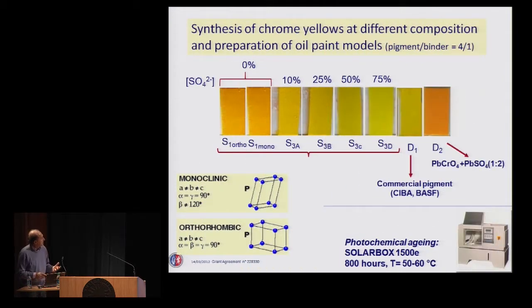And so what Letizia did to better characterize the knowledge concerning this pigment was to synthesize different composition lead chromates, and also those having different crystalline structure. So these are mock samples layered in oil. These are pure lead chromate in the orthorhombic system, pure lead chromate in the monoclinic system, and then co-precipitated with 10%, 25%, 50%, and 75% of sulfates together with chromates. And these are two commercial pigments. This is a commercial pigment, sorry, and this is a mixture, just simply a mixture, not a co-precipitate of chromate